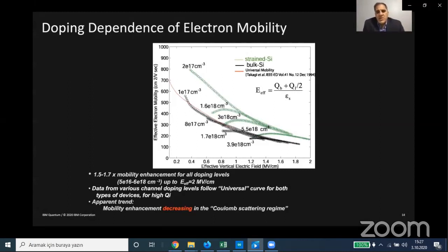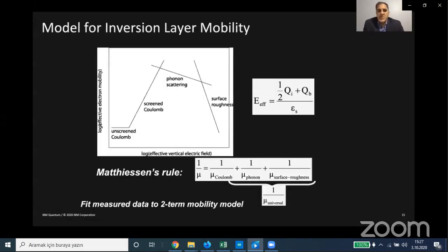However, as one can see here, at higher doping levels and lower vertical fields, the amount of mobility enhancement is reduced. And this was explained in terms of less strain improvement in the Coulomb scattering regime, which happens at lower field. This data was then fit to this Matthiessen's rule model, which essentially breaks out the regimes of scattering in terms of Coulombic scattering, phonon scattering, and surface roughness scattering.